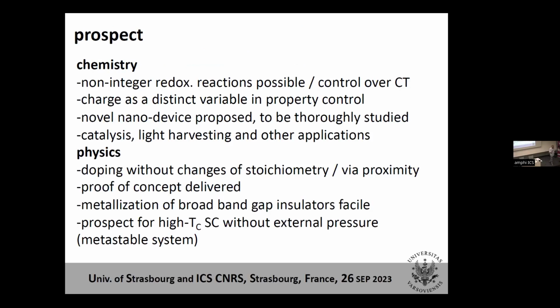So, also before I really close, I was thinking there are some zeolites, beautiful zeolites, which have hexagonal pores, one close to each other, which have a diameter of 3 nanometers. And the wall thickness between the pores is about 2 nanometers. So that's the right scale. If we were able to fill such pores with strong, for example, organic oxidizer and reducing agent close to each other, they would form this in a bit different setup, not really layers, but something similar. Unfortunately, the best nanopipettes we can have today have a diameter of 10 nanometers. And here we must have about 1 nanometer. So we are 1 order of magnitude too short to make this idea work in this setup. But maybe you have other ideas.